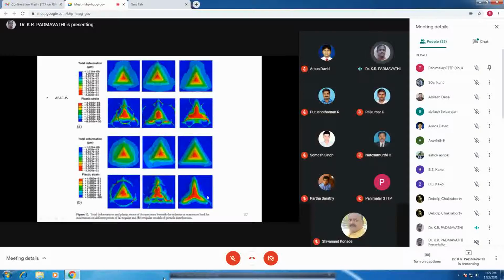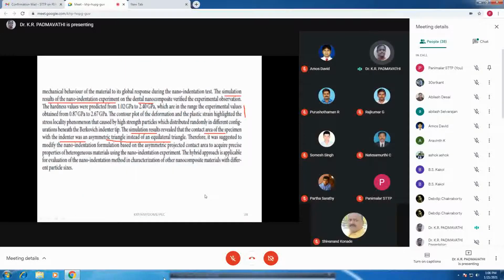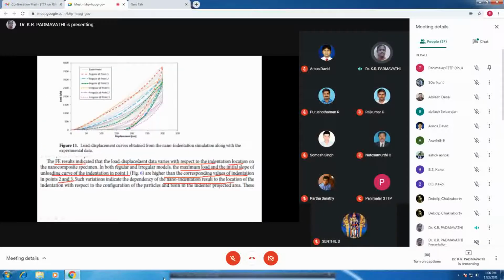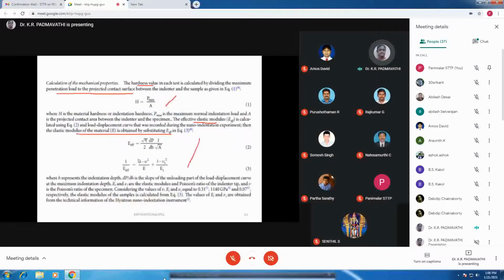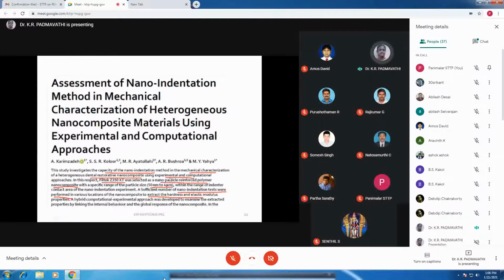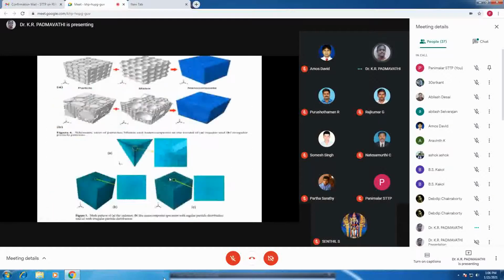These are the deformation and the stress distribution data they have taken for the regular model and for the irregular models. So as a conclusion, the simulation results of the nano indentation experiment on the dental nanocomposite verified the experimental observations. The simulation results actually revealed that the contact area of the specimen with the indenter was an asymmetric triangle instead of an equilateral triangle. So they have come to a conclusion. Instead of doing an experimental nano indentation, we can extract more information if we do simulation. That is the concept as specified here.